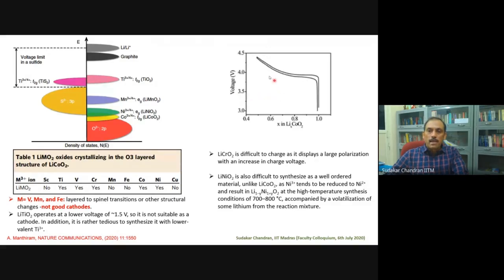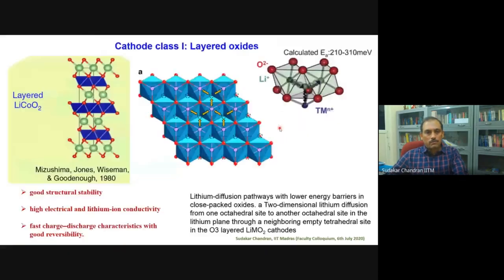They found that in LiCoO2, they could reversibly extract half of a lithium in this compound. It also gave a good cationic ordering. Basically, the cationic ordering arises because of lithium plus and cobalt 3 plus, because of the large difference in the charge and also the ionic radii, they don't mix up between these layers. Lithium sits in the octahedral layer on its own, and cobalt sits in its own octahedral layer. So the diffusion of lithium was much better in this compound. It had a very good structural stability.